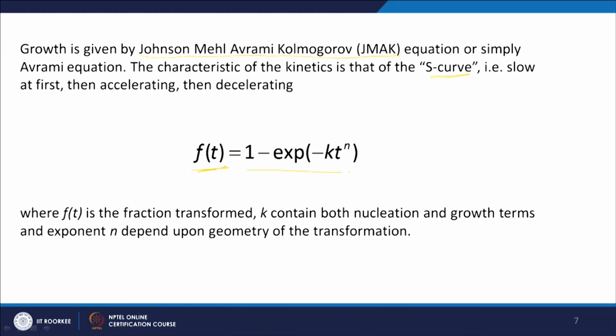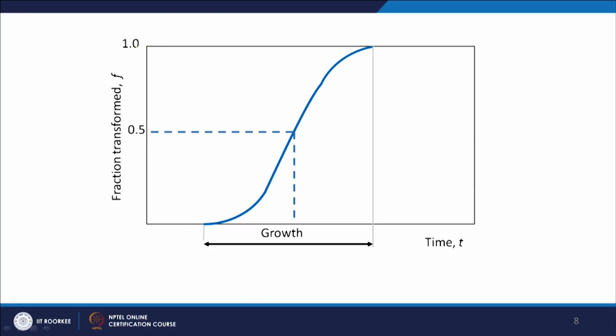And the fraction as a function of time will be given by an exponential expression like this, where Ft is the fraction transformed, K contains both nucleation and growth terms, and exponent n depends upon the geometry of the transformation. So, you do not have to worry about that right now. All these things will come into the overall growth kinetics. So, this is what your typical S curve will look like. On the y axis you have fraction transformed. 1 means it is fully transformed, 100% transformed.